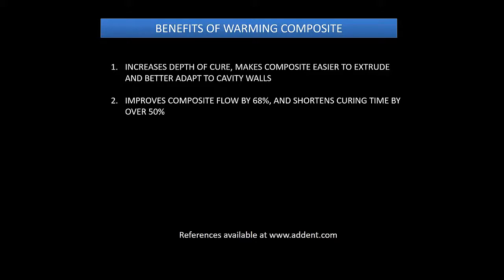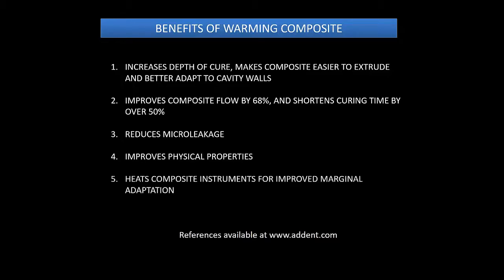And because it's warmed, it also shortens the curing time by over 50%. And this has been studied. It's really neat. That's a good feature if you're moving. You want to have the material move quicker, adapt a little better. Even taking these great materials, like in the Spectra line, you can alter the flow by warming them. It does not hurt any of the physical properties. It's been shown to reduce microleakage, give you better physical properties, and you can even heat the instruments if you like to use composite instruments to get better marginal adaptation.